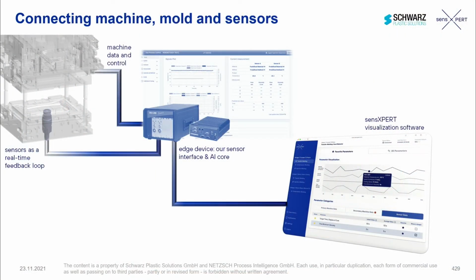How do we do that? We have connected our package to the machine environment. We have an edge device created by ourselves, where a huge software package is running, also equipped with artificial intelligence. We collect data from sensors out of the mold and we collect the machine parameters. At the same time, during data collection, our artificial intelligence algorithms are running and calculating quality criteria of the material, like glass transition temperature, like degree of cure.